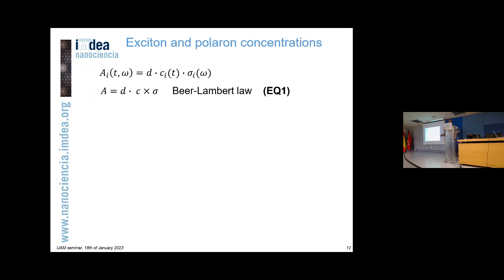So that was qualitatively, and we can look more quantitatively at the problem, because transient absorption is nothing else but an absorption experiment. Therefore, the signal you are detecting is given by the Beer-Lambert law: it's the product of time-dependent concentration and cross sections. So in principle, if one knows the cross sections of the different excited states, we can obtain the time-dependent concentrations.